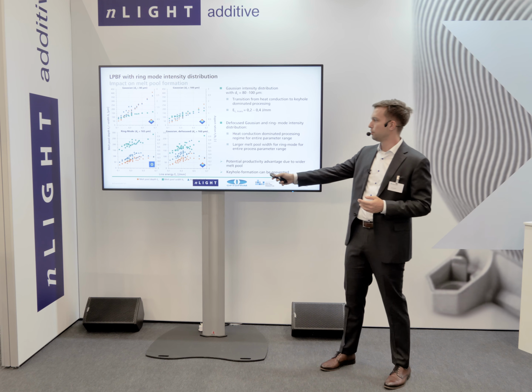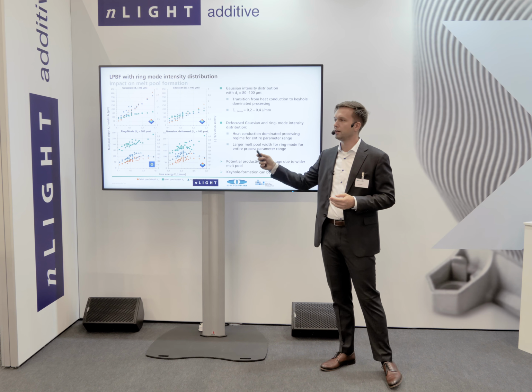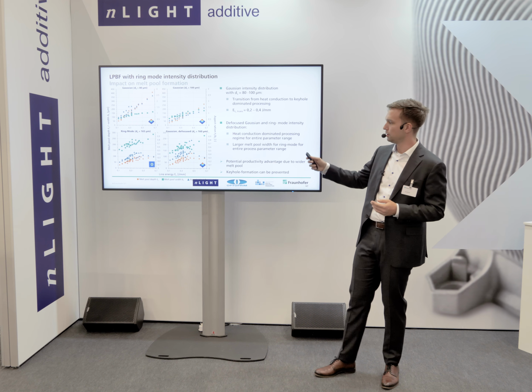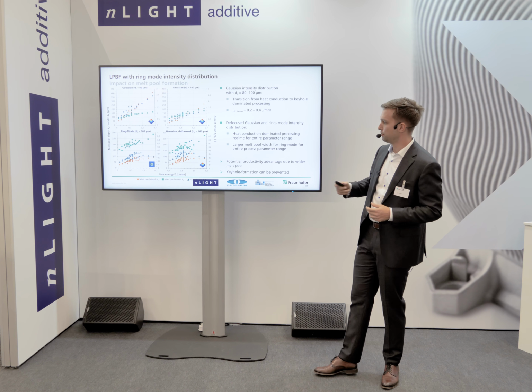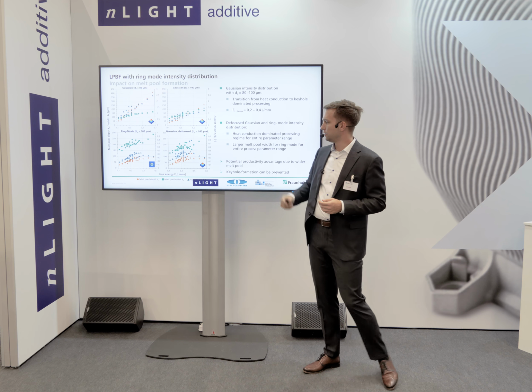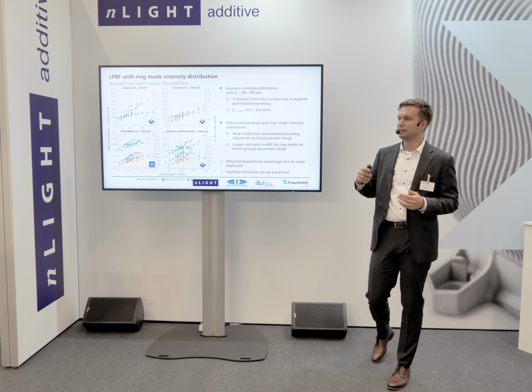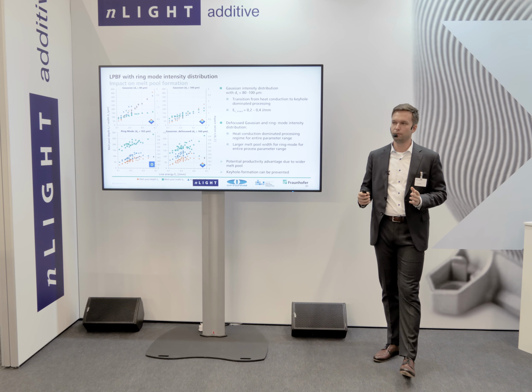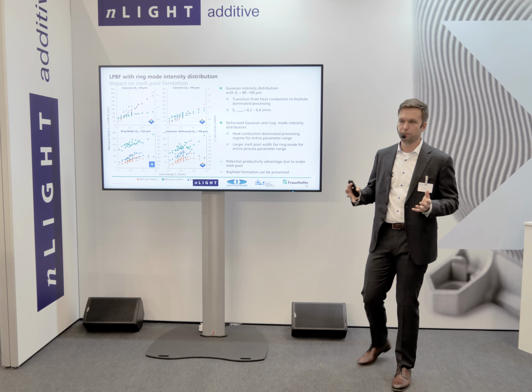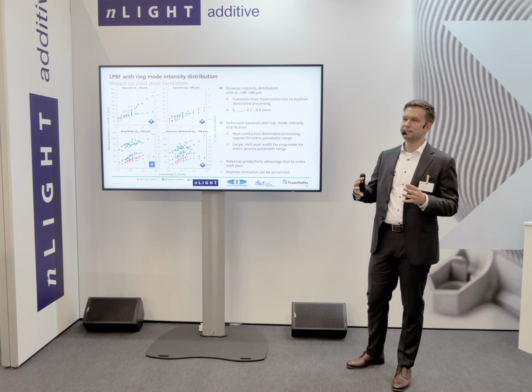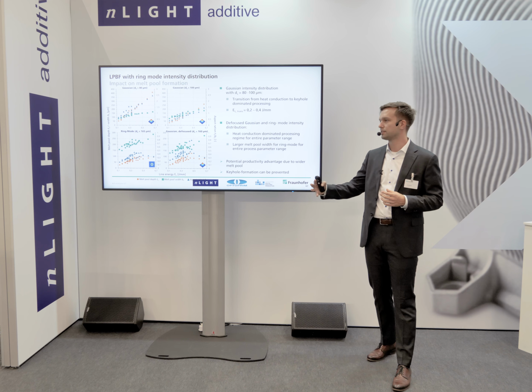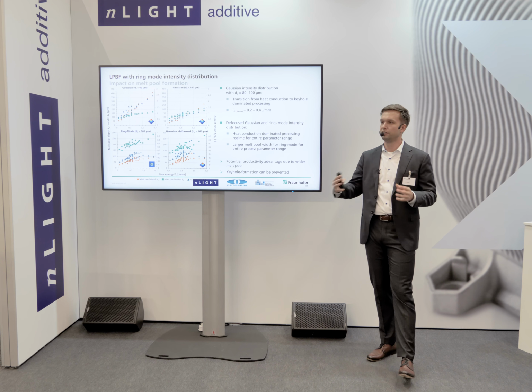And if you then compare the defocused and the ring mode side by side, you will also see that for the melt pool width, the ring mode is generally larger, independent of the processing parameters, which kind of makes sense because the intensity within the beam profile is more towards the sides of the laser beam instead of in the center.